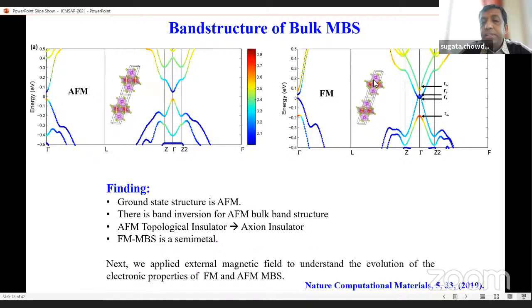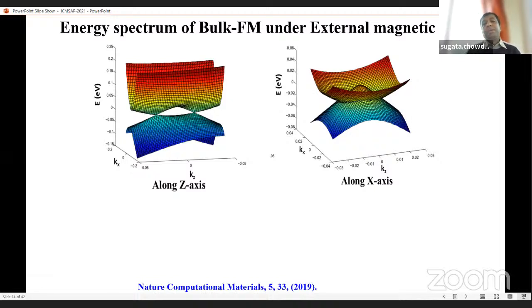Which direction is our magnetic system? If you notice, the magnetic moment of this manganese system is out of plane, along the z direction. Is it possible that the property will change if we apply the magnetic field in plane? So we considered the magnetic moment out of plane and in the in-plane direction. You notice the semi-metallic behavior of the material is not changing. Previously we got two nodes, and here we get a circle, which is called a nodal line. So the semi-metallic behavior is not changing, but what changes is the band structure.